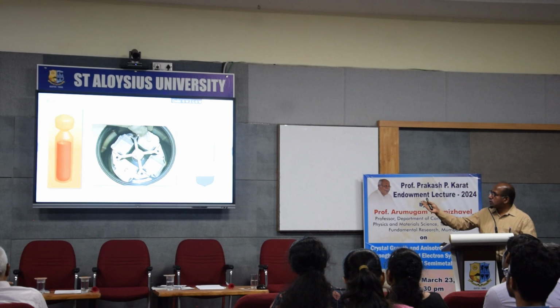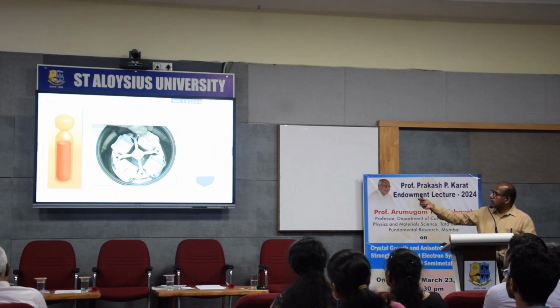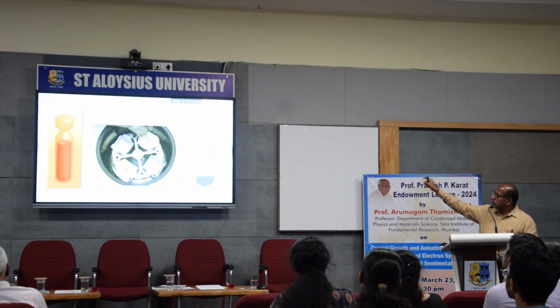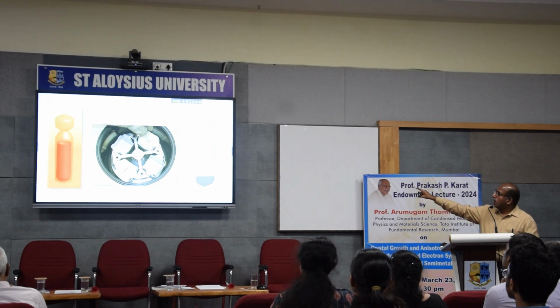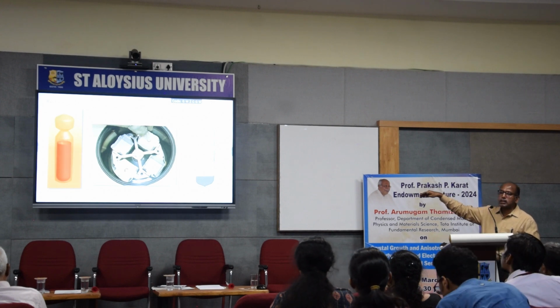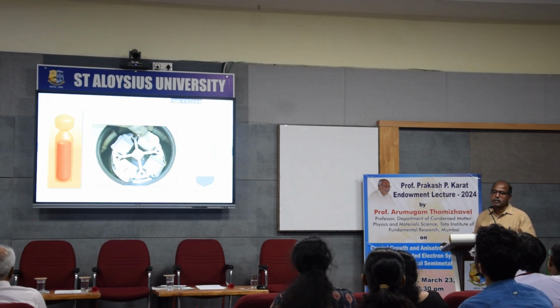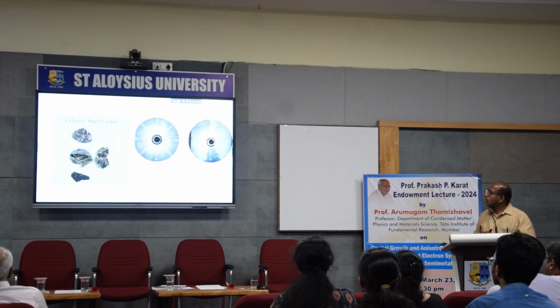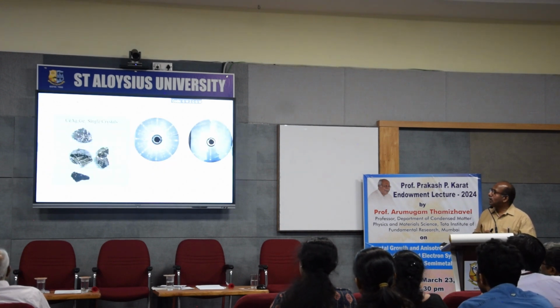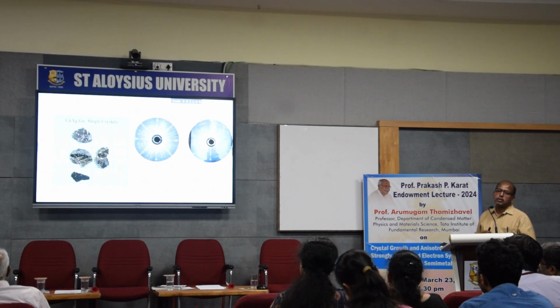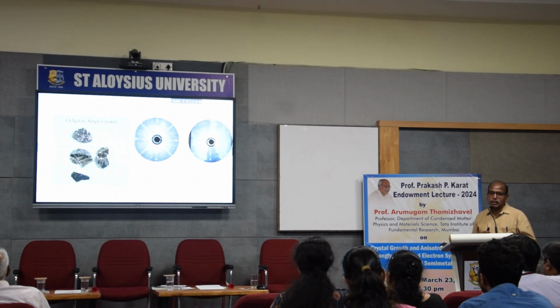So for that, we know the melting point of this eutectic composition is 650 degrees centigrade. I heat up to 750 degrees centigrade, take this ampule out of the furnace, put it upside down in a centrifuge, and spin the centrifuge at a very fast speed so that the liquid comes out and the crystal still remains inside the crucible, so I can separate out the crystal. So these are the crystals that we have obtained, and the first thing we do is the Laue diffraction to find out if it is a good single crystal. This diffraction pattern confirms that they are single crystalline, and we have studied the anisotropic properties.